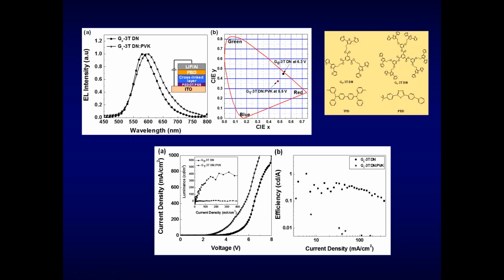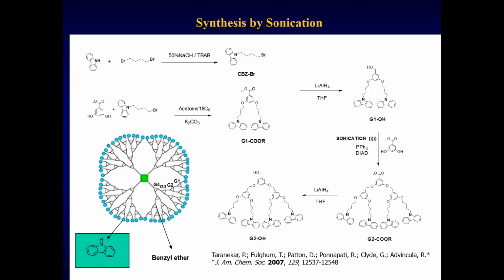Now, from thiophene, we actually investigated other types of carbazole-based electroactive monomers. In this case, utilizing, again, a convergent method, we synthesized carbazole-terminated polyether dendrimers. By synthesizing this first route to produce your AB2 monomer, you will end up with a G1 dendron. And then after reduction of the ester, you can terminate this with an alcohol. This becomes the AB2 monomer for the generation 2 dendron.